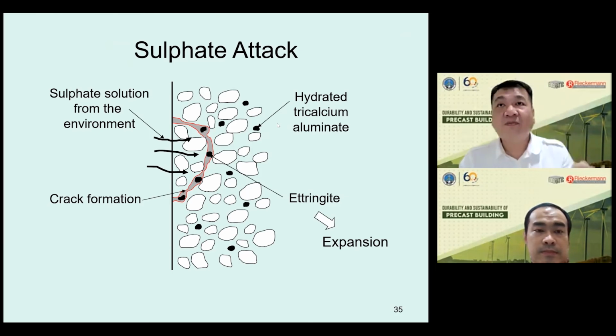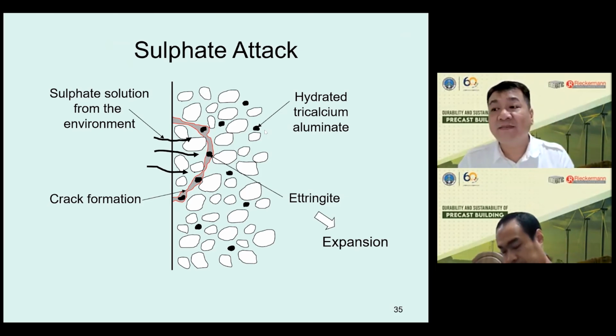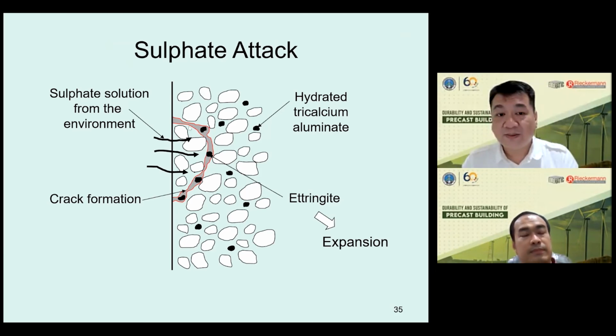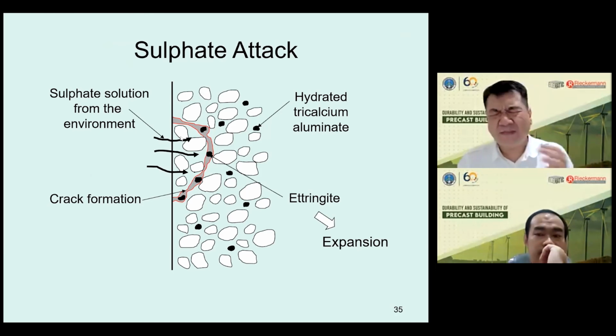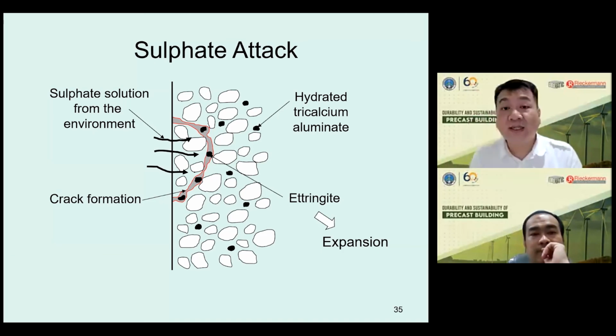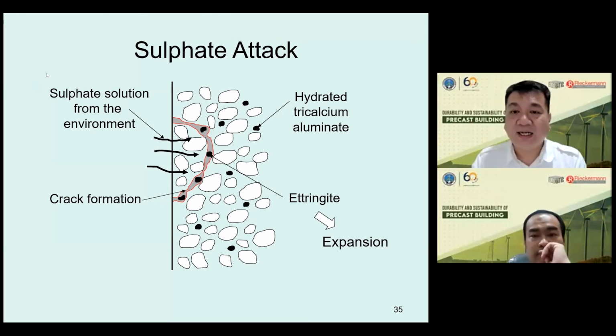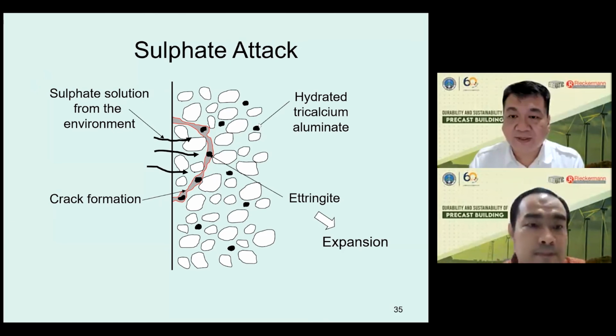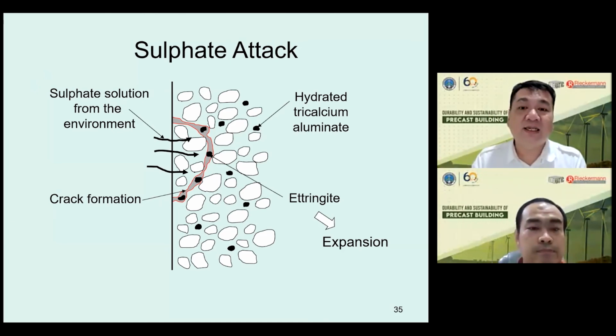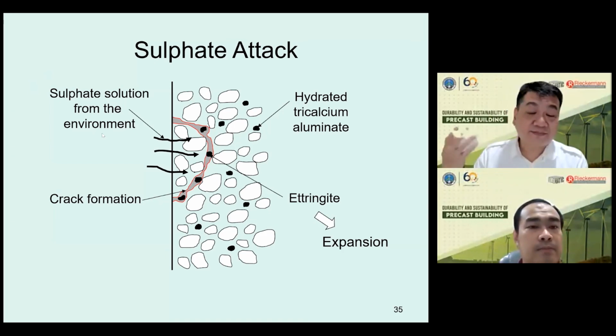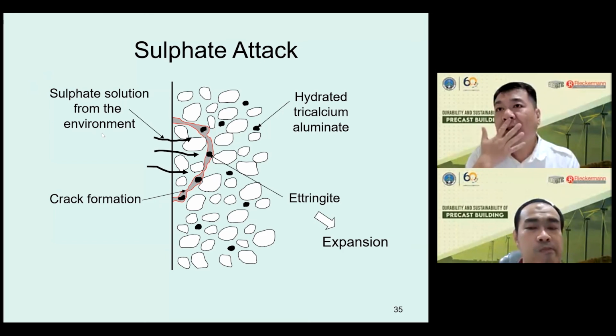So concrete with fly ash or concrete without fly ash, I think there's a similar tricalcium aluminate there. So the response will be maybe the same. But then again, when you are replacing some part of the cement with the fly ash, meaning that the content of cement is lower, it could be beneficial to use fly ash in the marine environment, because the content of tricalcium aluminate will be relatively lower. That is the answer. But with the same strength, with fly ash or without fly ash, I don't think it will matter too much. I think that is mostly due to the tricalcium aluminate content.